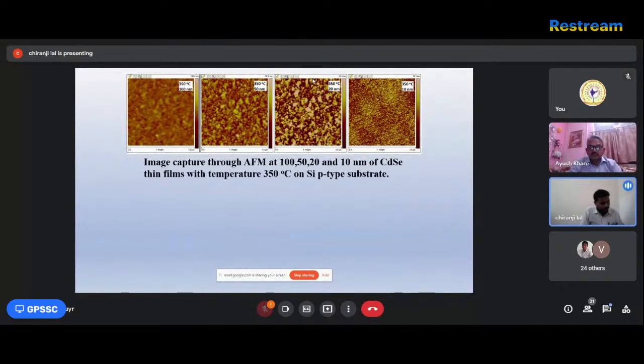Other structural parameters like lattice spacing, lattice constant, dislocation and micro strain, also the band gap of CdSe thin film studied by UV-visible spectroscopy. Other optical parameters are also influenced by the increase of annealing temperature. According to all surface morphological, structural and optical data, it is clear that this is a very useful technique to deposit highly efficient thin film. Thank you.